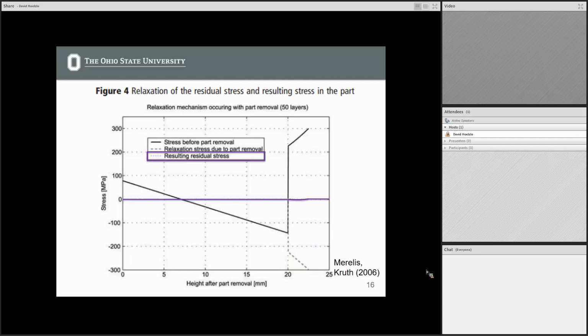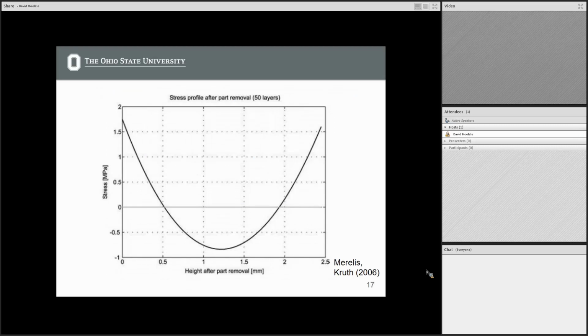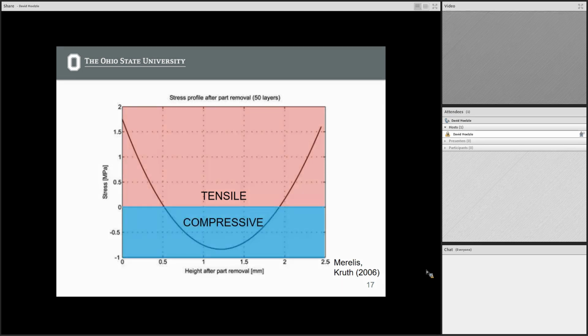I tried to highlight that little tiny dip right there. But blowing that up, this is what that's going to look like. You can see that we get a really big decrease in overall residual stress from the part being on the base plate itself. And we get two distinct zones at either end of the part of tensile stress, and in the middle we have a broader compressive stress zone. And also that the endpoints aren't actually at the exact same stress level. The maximum stress comes at the section of the part that's towards the base plate itself.